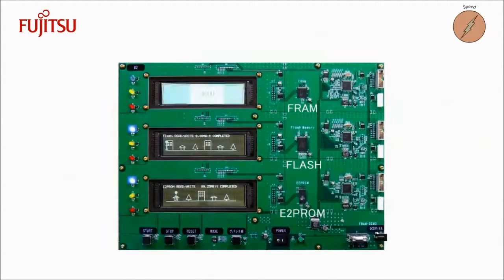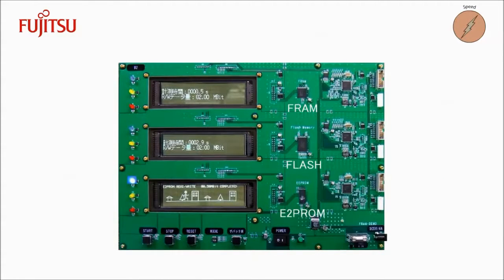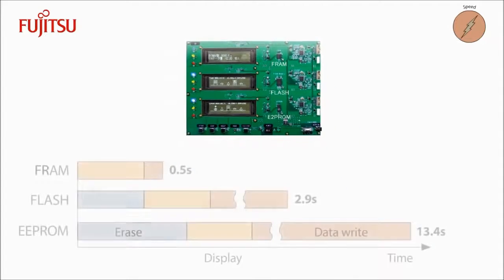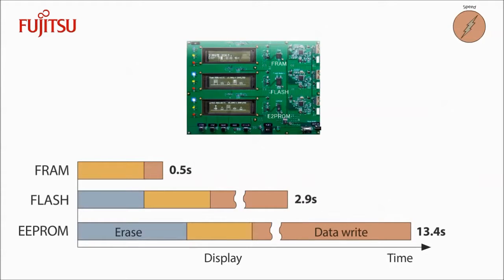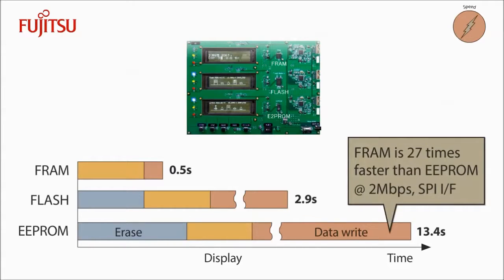Here is a real-world demonstration of FRAM's superior performance. In this demo, FRAM, Flash, and EEPROM have been placed on a single board. The test uses the same data size and transfer rate for each memory type. As you can see, FRAM is significantly faster than either of the other two non-volatile memories. FRAM completes the test in half a second, compared to 2.9 seconds for Flash and a full 13.4 seconds for EEPROM to complete the same task. FRAM could run even faster, if not limited by the SPI transfer rate.